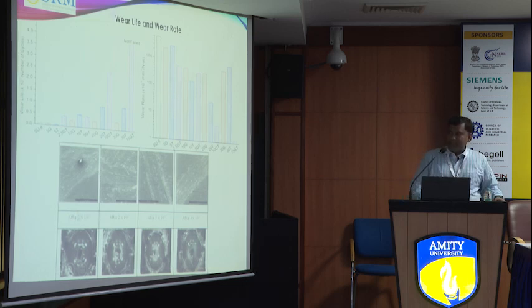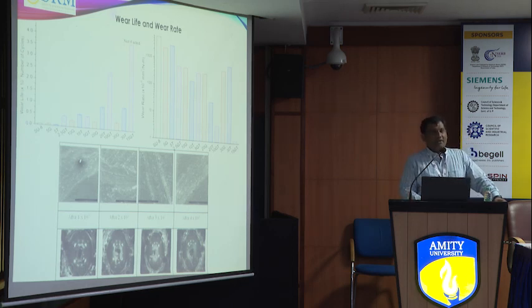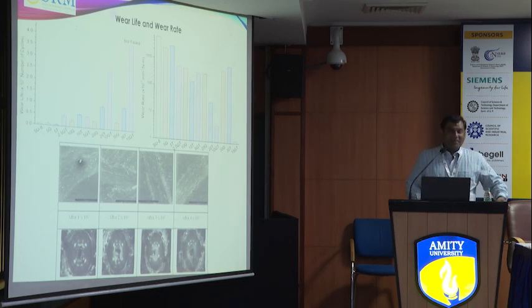So this we can also see by looking at what happened in every lakh cycle. You can see here after 1 lakh cycles I took the pictures, and at the interface also there is very little debris. 2 lakh cycles also very little. At 4 lakh the coating is still there on the surface. So that was the beauty in this work. But we were not able to achieve below 0.1. That was the main goal.